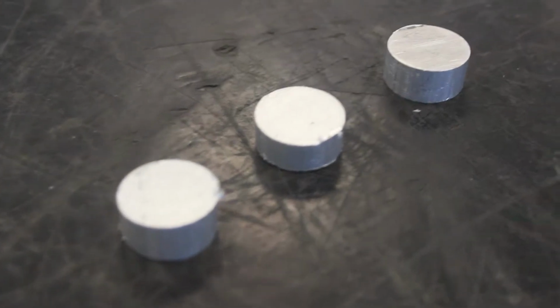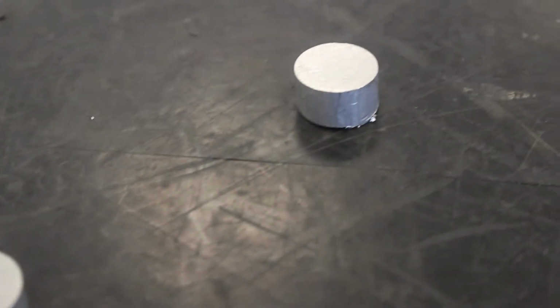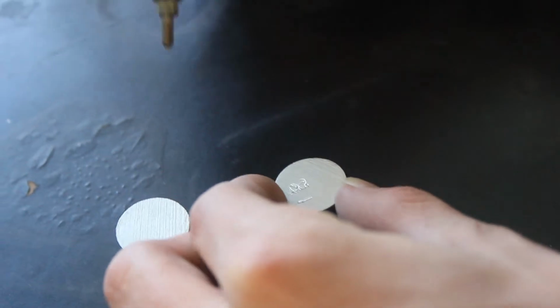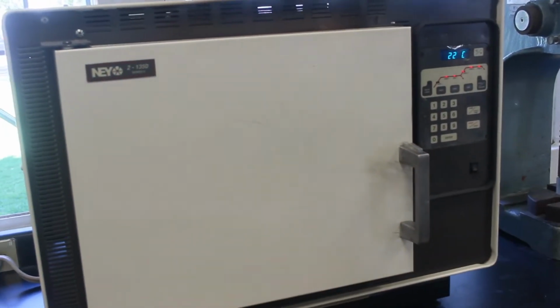Also, we wanted to analyze the microstructural and hardness changes during these various stages to identify how it changes over a long time. For this lab practice, the materials we needed were 6 specimens of a 6061 aluminum alloy, an electric oven as the muffle in order to heat, the Brinell and Vickers hardness equipment to obtain our results, and also the protective equipment for when we inserted the material into the heat treatments. Those were the only materials that we used for this lab practice.